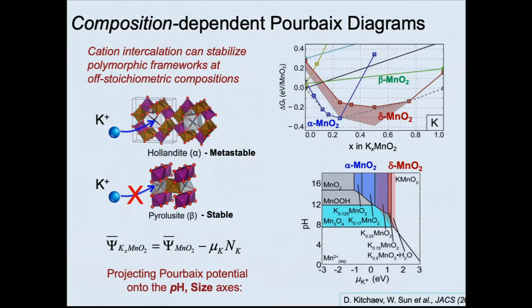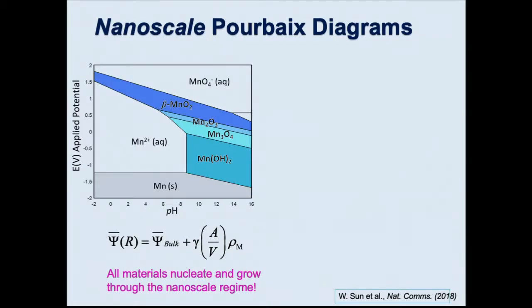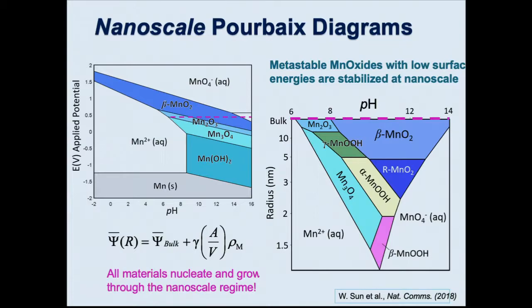I'm going to go a little faster. We look at phase stability as a function of potassium content. Then we look at it as a function of size, and this is really the cool one. Again, this is the bulk phase diagram. This one I'm going to spend a little more time on because this is now a phase diagram as a function of size. This is at a fixed potential because it's a three-dimensional map, so I have to slice it somewhere. This is the pH axis. This is size, bulk here. This is small, right? So this axis is this line here. And what you see in the bulk is you have only manganese 2O3 and beta MnO2.